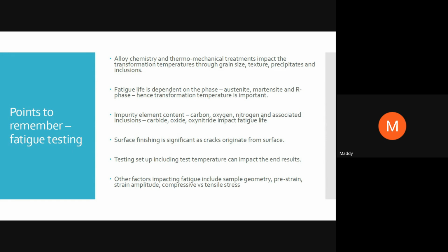Now, fatigue crack originates from the inclusions on the surface. So the surface finish also plays a role in your fatigue properties. Last but not the least, the testing setup is extremely important. You have what's called RBT, rotating beam fatigue testing, which is used, but there are also other setups where they use a diamond-like profile and test the fatigue life. The temperature at which the sample is being tested is extremely important, because when you cycle it between austenite and martensite, heat is evolved and heat is absorbed, and that heat itself can impact your stress levels.